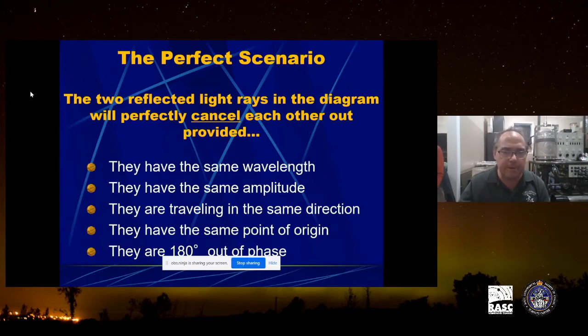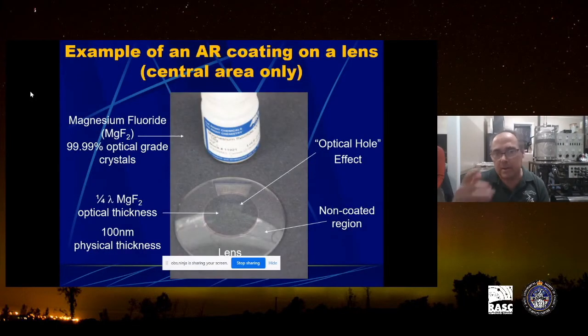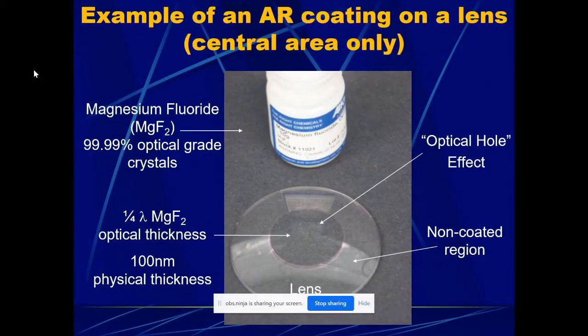Well, that gets a little bit more complicated. I won't get into it, but that's what multiple coatings are used for. But here's the effect that you would see. When you coat a lens, let's say just in the center part, we create the optical hole effect. And normally when I give this talk live, I pass around this lens, and no matter how you look at it through the light, you can't see any glass there. The only way to tell it's glass is by touching it. Then you get fingerprints on it, and then everybody gets upset. But anyway, this is the effect that happens.